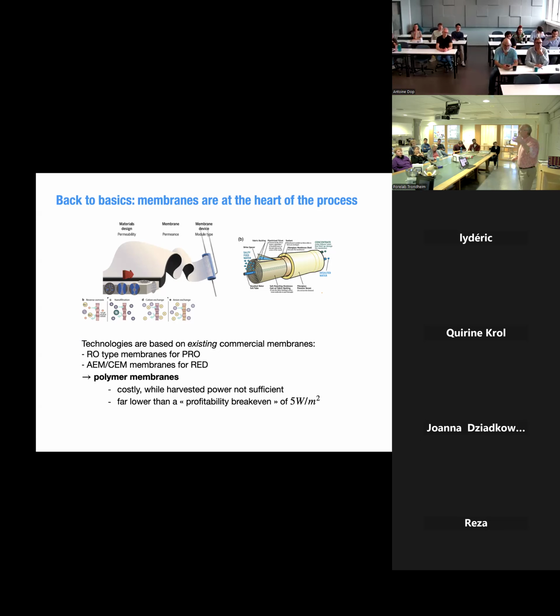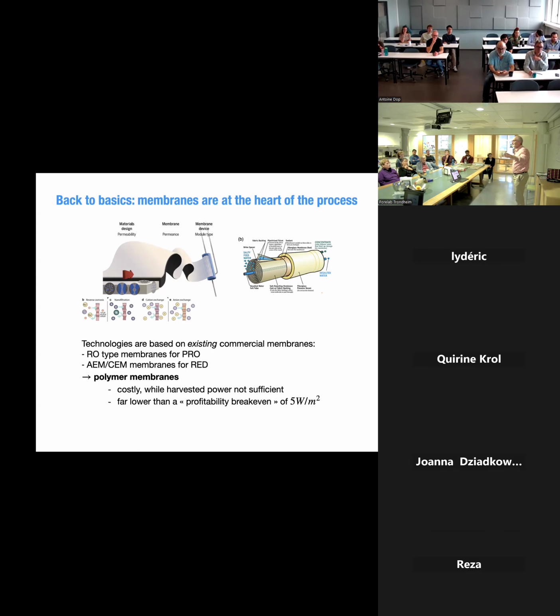And actually, typically with PRO and the other technique, RED, at a large scale right now, you reach a fraction of 1 watt per square meter of membrane, which is quite small. And actually, there is a number, we were discussing this with Signe last time, a kind of profitability break-even, which you should go above 5 watts per square meter so that it becomes interesting to make a real pilot plant at an industrial scale. So right now we are far below that.